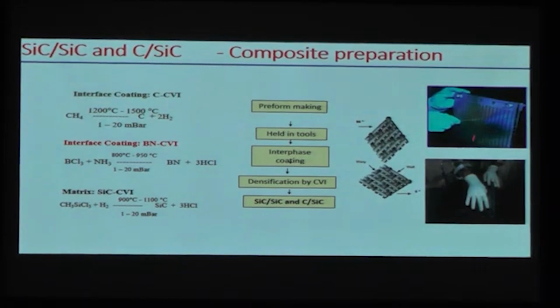First you start with the preform making. Here basically we take the 2D fabric and cut it into fabric layers, then stack 0 degree and 90 degree and repeat till you reach the thickness. Then you also stitch in the Z direction so that the interlaminar shear strength will be more. And once the preform is ready, it will be put into a reactor.